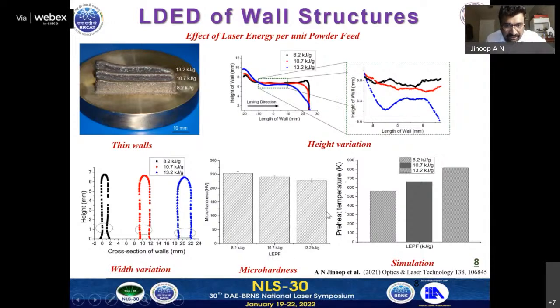Then we found the variation in the micro hardness and microstructure, and we could see that the mechanical properties are better than the conventionally built samples, and a slight reduction in the hardness was observed with an increase in the LEPF values. To correlate these experimental values, we did a numerical simulation to predict the preheat temperature, that is the preheat temperature on the build surface after deposition of a particular layer. We could see that with an increase in the LEPF, the preheat temperature increased, which resulted in the reduction of cooling rate, leading to a coarsening of microstructure, leading to reduction in the micro hardness values with an increase in the LEPF values.